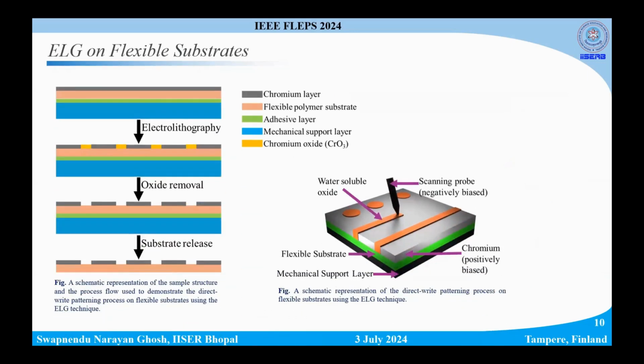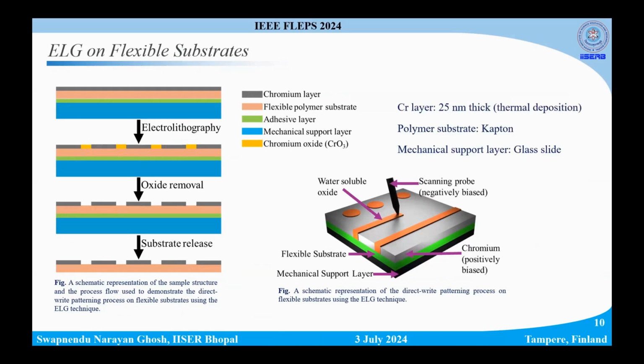We tried to replicate the same thing by depositing chromium on a flexible substrate. We tried to follow this process flow. This is just a schematic of the process that we tried. These are the sample parameters, the sample description that we took. The chrome layer was thermally deposited, 25 nanometers thick. The polymer was a Kapton layer, and for mechanical support we used a glass slide.